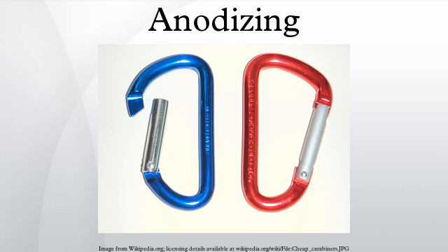The shade of color produced is sensitive to variations in the metallurgy of the underlying alloy and cannot be reproduced consistently. Anodization in some organic acids, for example malic acid, can enter a runaway situation, in which the current drives the acid to attack the aluminum far more aggressively than normal, resulting in huge pits and scarring. Also, if the current or voltage are driven too high, burning can set in. In this case the supplies act as if nearly shorted and large, uneven and amorphous black regions develop.